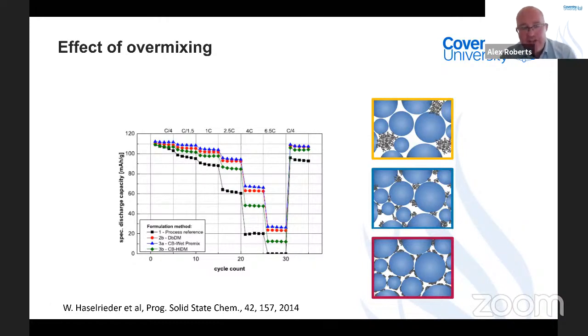Now, one thing that I would say, if you're looking to see how consistent, how effective your mixing is, one thing that I do like to look at is the rate behavior over a number of cells. If you've got very effective and consistent mixing throughout your electrodes, you do a number of repeats, and if they are close together, if they're closely matched in performance at the lower rate, you will also see a closely matched performance at the higher rate.